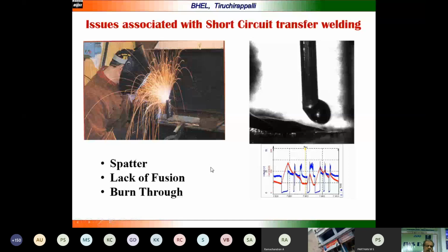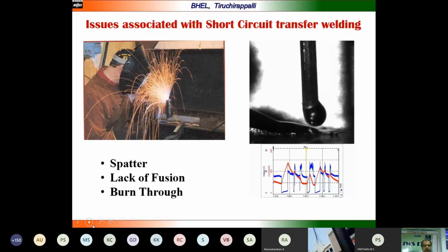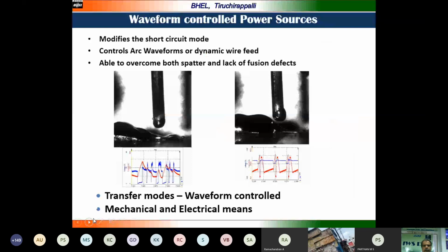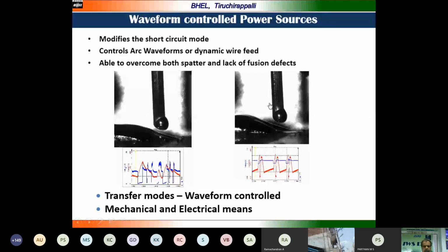The modified waveform control power sources modify the short circuit mode and control the arc waveforms or dynamic wire feed, and are able to overcome both the spatter and lack of fusion defects. What you are seeing are the transfer modes and waveform control modes, and the mechanical and electrical means are used here, and you can see how the arc is getting deposited here.